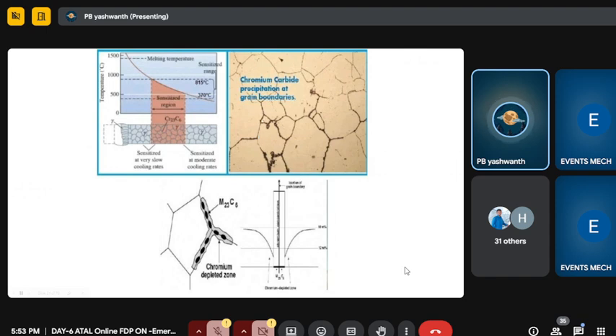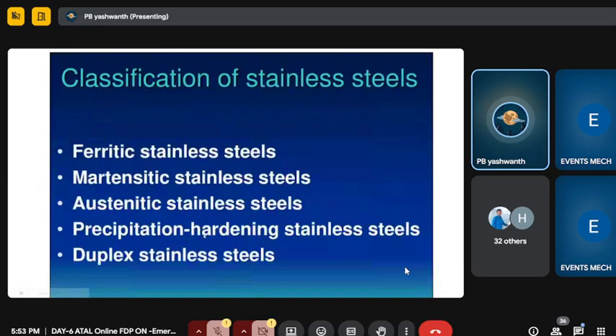The enriching of the grain boundaries makes a difference in the strength between the grain and the grain boundaries, which may cause a kind of corrosion, which will cause stress corrosion cracking or otherwise intergranular stress corrosion cracking. You can see how those intergranular cracks in the grains form due to the boundary corrosion, which is caused by M23C6, because the depleted chromium goes and accumulates on the boundaries, making the grains weaker. So this is the significance of the amount of chromium in the 316.